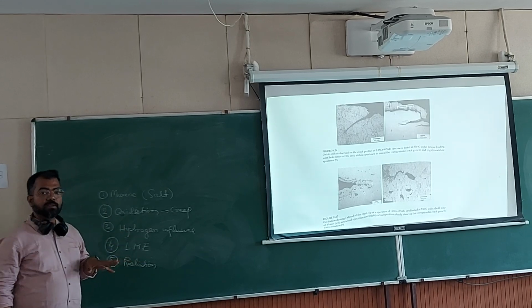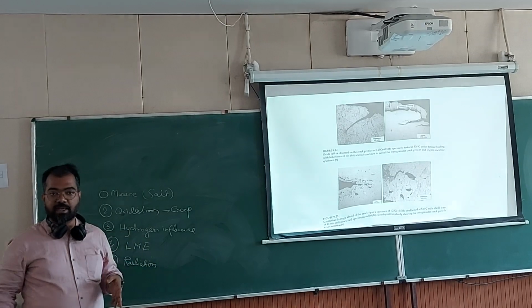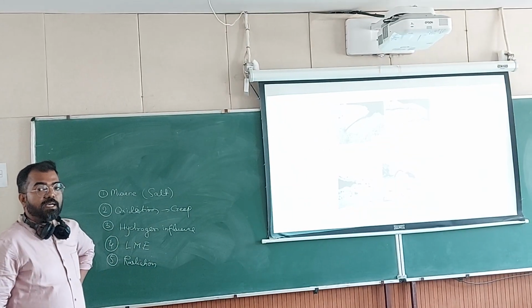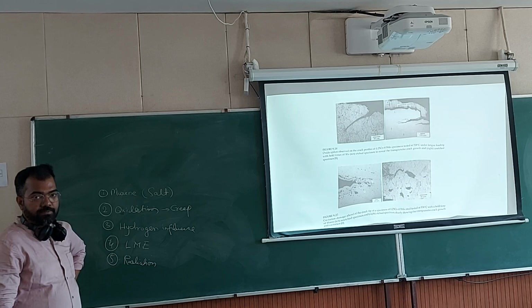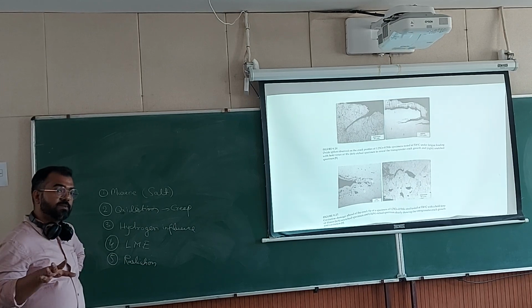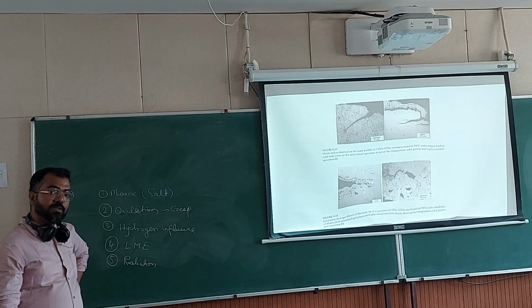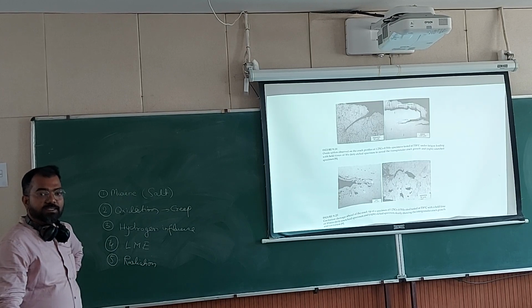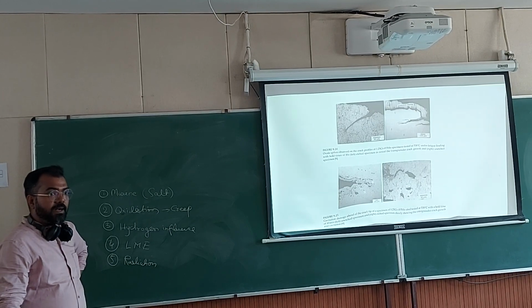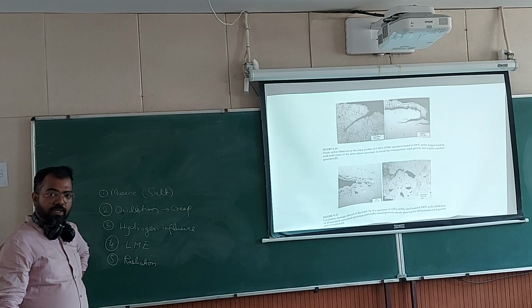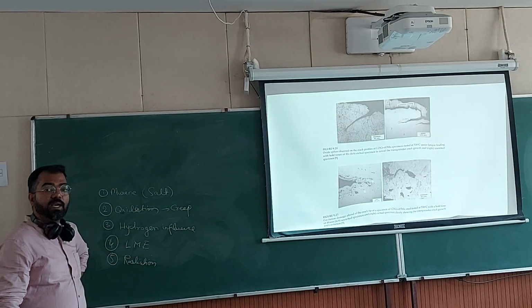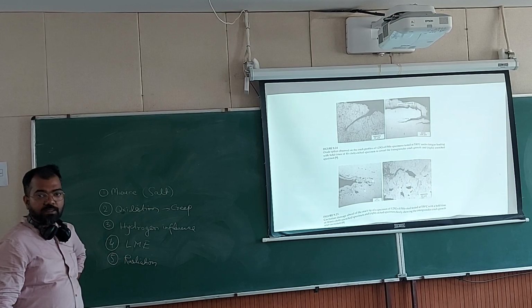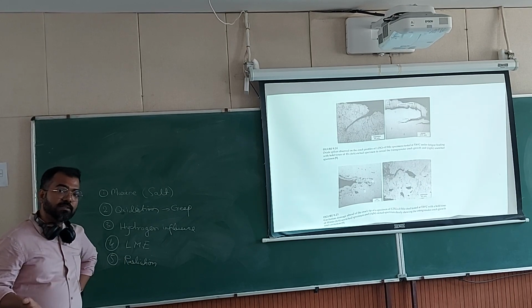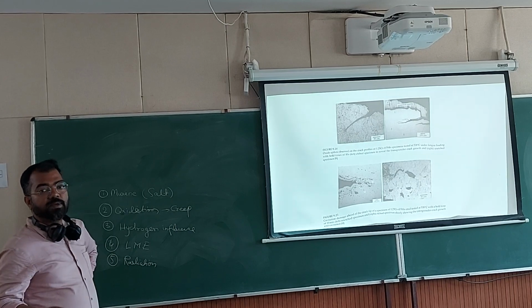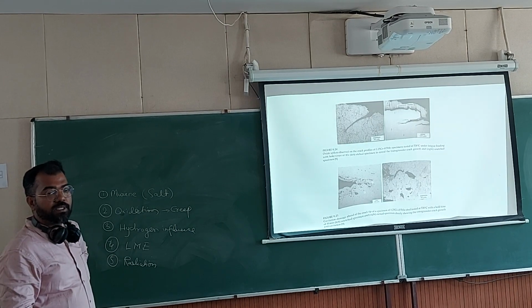Hydrogen influence happens because hydrogen is picked up while manufacturing, and the second pickup of hydrogen can happen when you are welding. So when you have covering gases, from that gas hydrogen can be picked up. If you don't have those gases, then oxygen will be picked up. Okay, so hydrogen can come from there. Apart from that, those are not very gigantic application areas. Welding is, because anything you want, you have to weld it. But there are various options of welding. Okay, so you can have laser welding, EB welding. Not all the components you can do in that way.